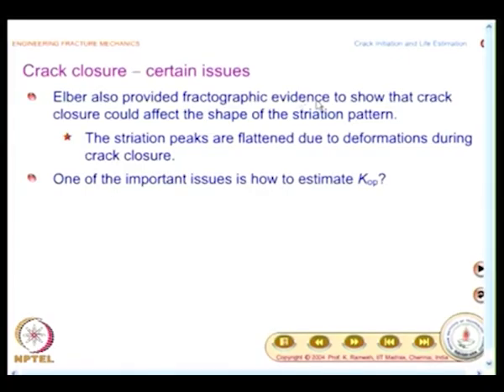So, in the case of Elber, when he reported the crack closure, later he also provided fractographic evidence to show such a thing happens, and the effect is the striation peaks are flattened due to deformations during crack closure. And as I mentioned, one of the important issues is how to estimate the stress intensity factor corresponding to fully opened crack.